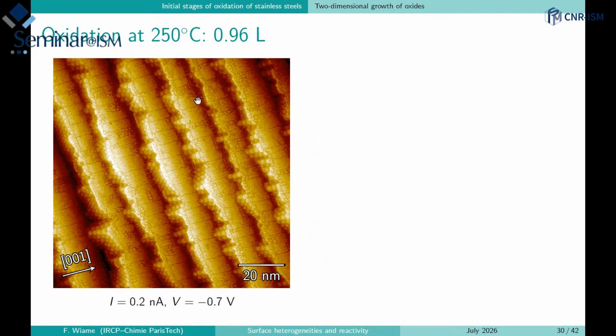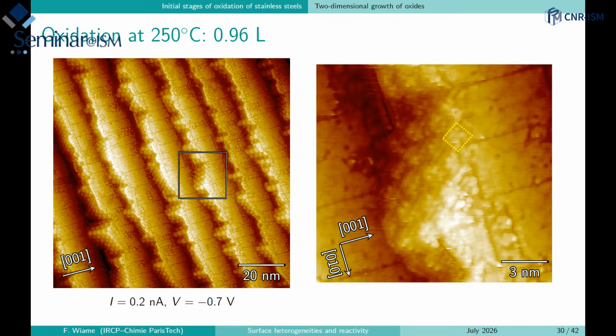So if we now look at the structural evolution as a function of exposure for the very beginning of oxidation. So this is about 1 Langmuir, so the equivalent, say, of 1 nanosecond at atmospheric pressure. We have a change which is limited to the step edges. You have here some islands which are formed, some nanometric islands, about 2 nanometer square islands, which are formed at the step edges, which are in fact chromium oxide, because as we have the 2 techniques in the same platform, we can do on the very same surface the chemical and the structural characterization. Here in photoemission, we just have chromium oxide, so we know that what is appearing is only chromium oxide.